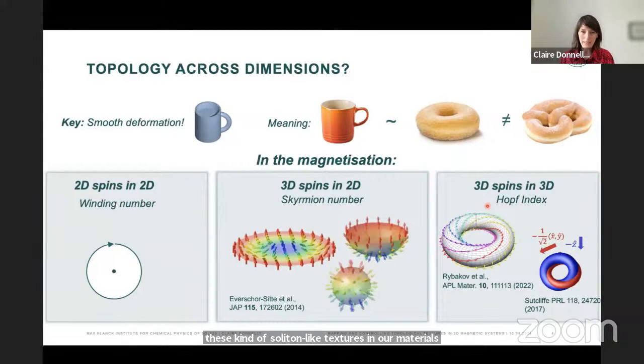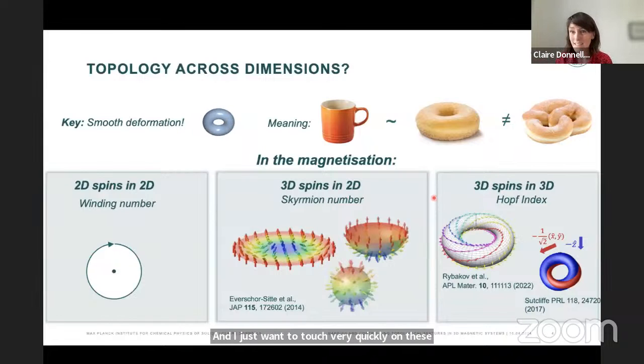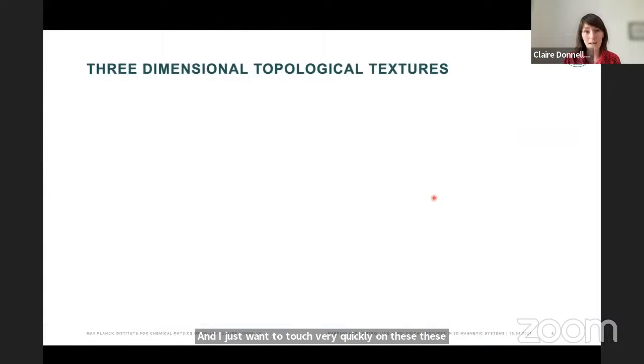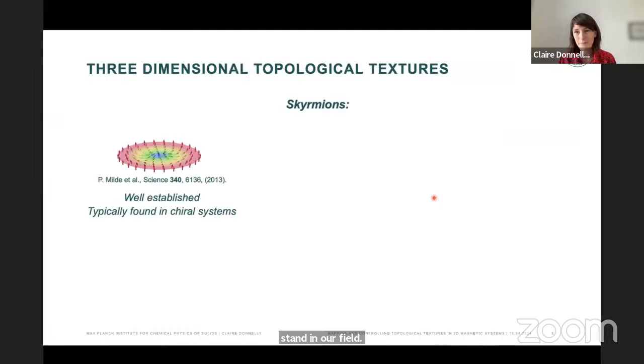So if we think about these 3D magnetic configurations, I would say we have different possibilities to really look at three-dimensional topological configurations. And I just want to touch very quickly on these last two and give you a bit of an overview of where we stand in our field. So if we start off with skyrmions, for example, these are very well studied configurations. There's been a huge amount of work over the last decade or more, and they are often observed or typically found in chiral systems. So they're associated with chirality.